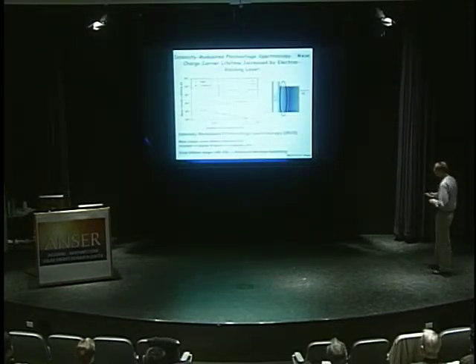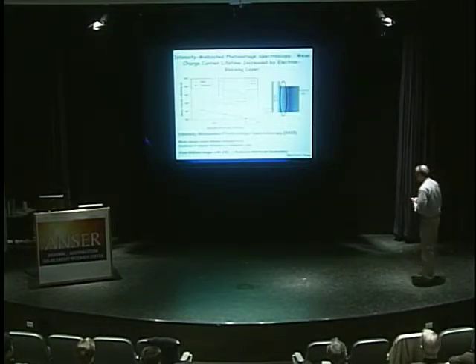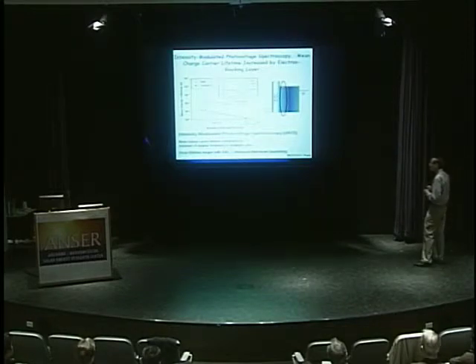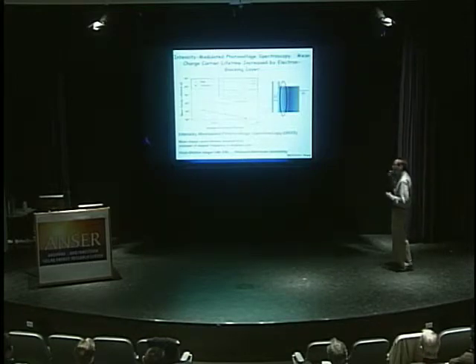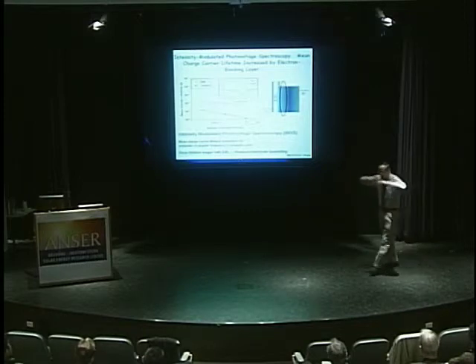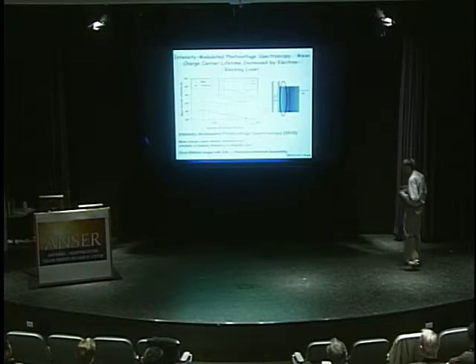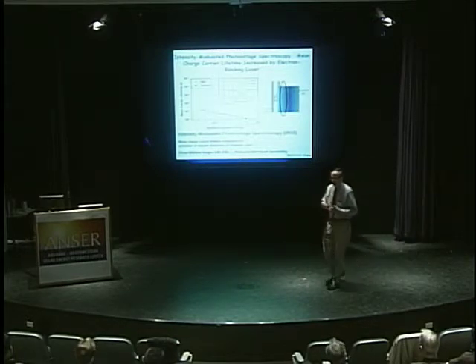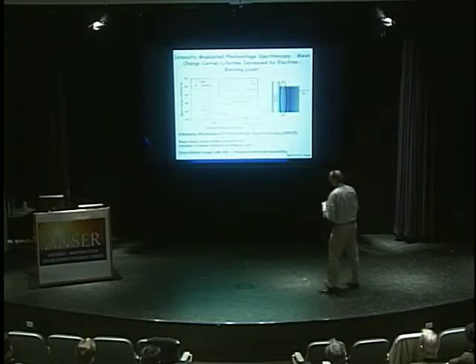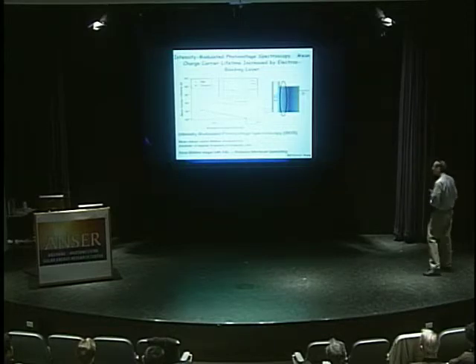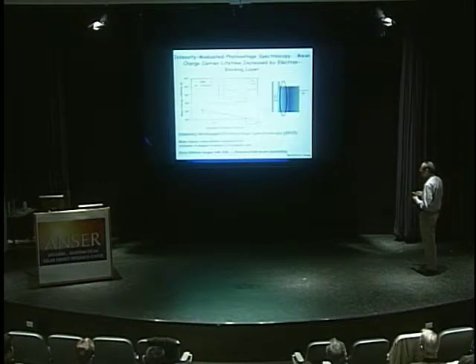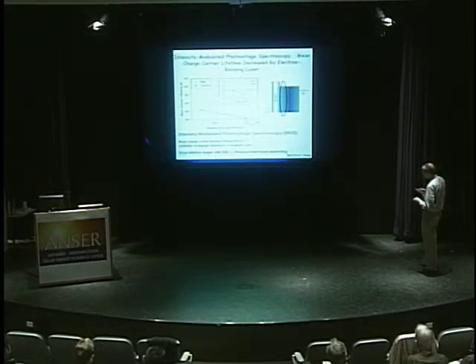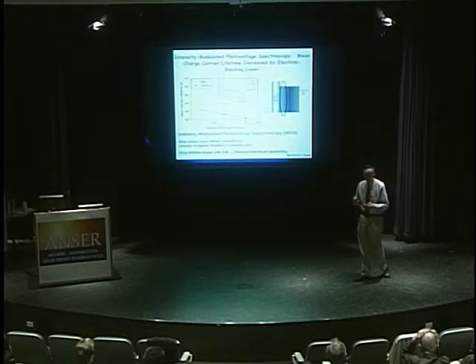Another experiment we did, I think Alex Martinson is in the audience, so Alex, and Alex is a student of Joe Hupp's. So we did an experiment which is like an impedance experiment. It's called intensity modulated photovoltage spectroscopy, IMVS. And so what you do is you have a light on the cell, but on top of that there's another pulsed light, and you can measure the lifetime of the carriers. And when Alex first got this data, or both Alexes got this data, it was really pretty remarkable, because the lifetime of the carriers, and our interpretation has to do with recombination at the interface, increased dramatically. And we've since done a lot of other experiments, and they're all in line with the picture that the longer carrier lifetime is associated with reduced interfacial quenching right at the interface by coating the ITO with this layer. In fact, we've seen the same thing in OLEDs as well.